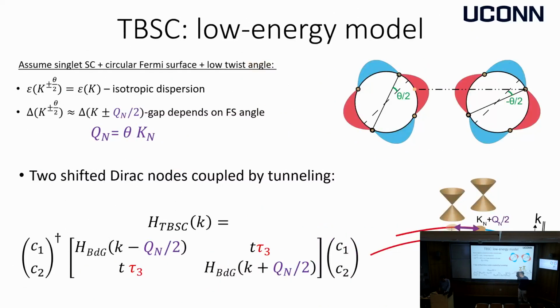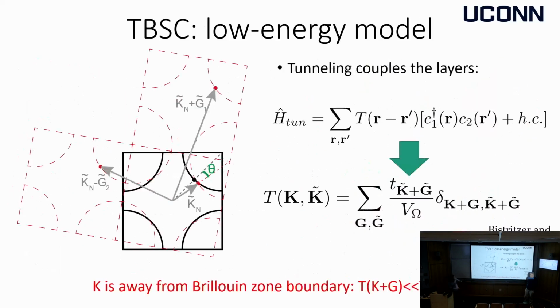In Bistritzer-MacDonald, you have not just two displaced Dirac cones, but three relevant tunneling directions because you're at the corner of the Brillouin zone. So you have to add another two, and then you can hop even further in momentum space, and you go on and on. In principle it's not possible to solve the problem exactly, so you either do perturbation theory or solve it numerically. Here, you can neglect all those other couplings because they arise from tunneling in higher Brillouin zones, and they are exponentially suppressed, as long as this point is close enough to the gamma point of the original Brillouin zone.